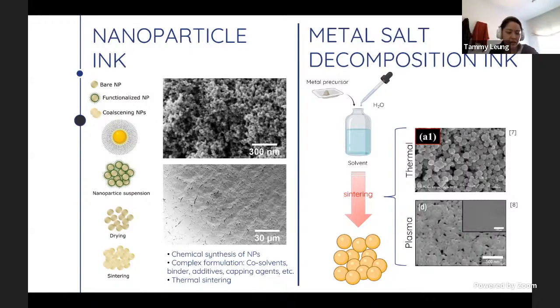The development of such inks is actually a very complex process, which requires the chemical synthesis of nanoparticles and the addition of additives, capping agents, co-solvents, and binders in order to stabilize the nanoparticles, as they are more prone to agglomeration due to their high surface energies. This in turn further increases the sintering temperatures and therefore limits the use of thermosensitive substrates. Typical post-treatment is through thermal heating, which results in films that are stacked, separate nanoparticles, and are extremely porous, where you can only see a slight necking of the nanoparticles together.